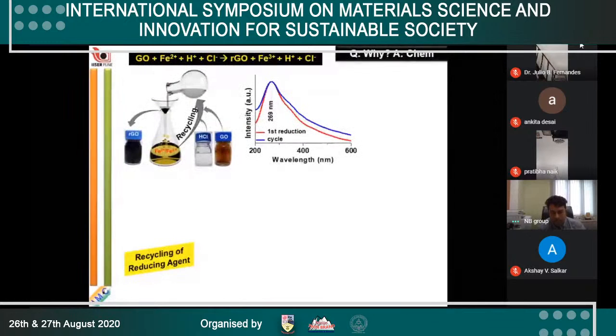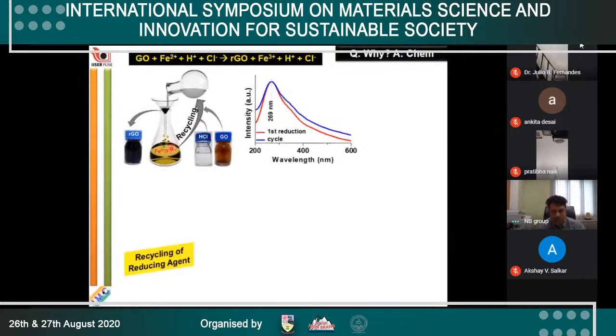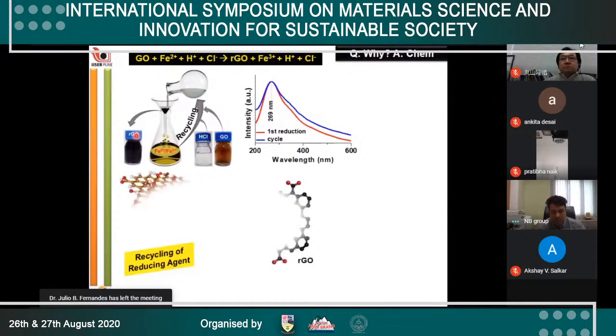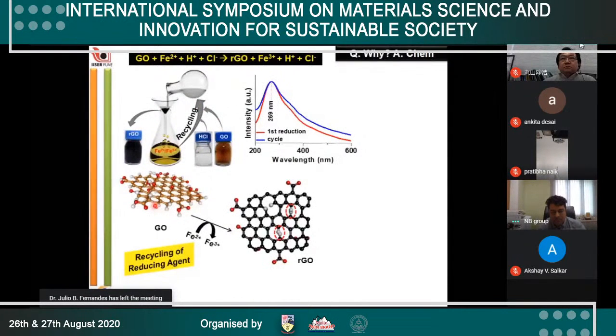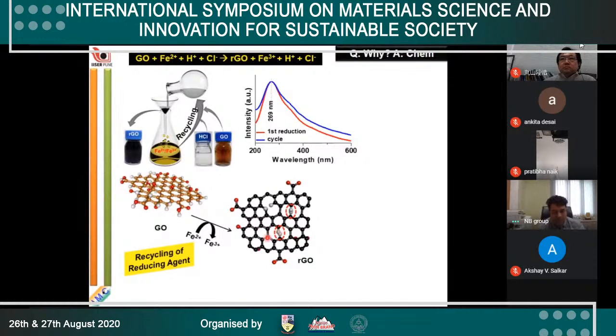It is because of novel chemistry. We found that the filtrate after one batch of reaction can be used for the second batch of reduction of GO to RGO. So what is happening? GO is getting converted to RGO. This is the reduction at the cost of oxidation of iron 2 to iron 3.